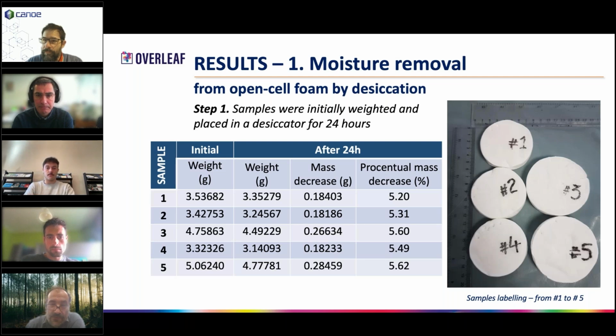On the left, you have the weight of the samples initially, and after 24 hours, a mass decrease from the desiccator. Please notice that this desiccator was with a kind of moisture trapping material, and this is current practice when we try to eliminate moisture from different materials. It is not the best. It is just a conventional use. It's a very well used practice in this cryogenic field. On the column on the right, we present the percentage mass decrease of these samples. It can be seen that for this particular material, the values were around 5%.